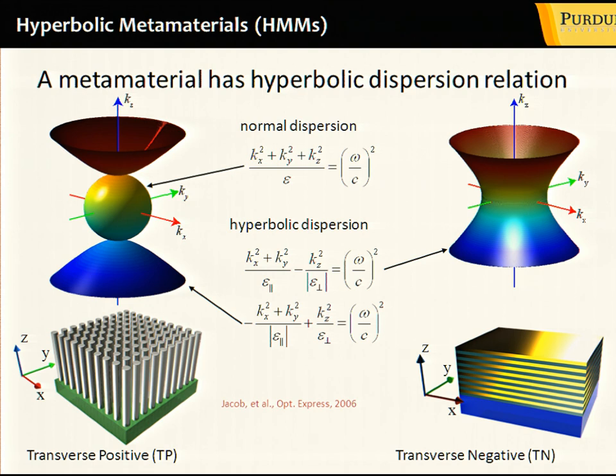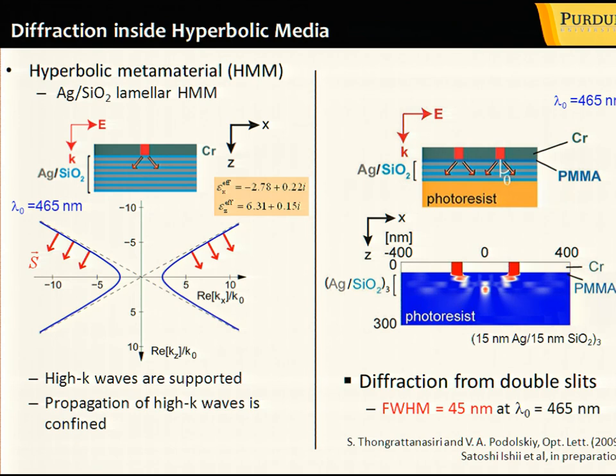However, if one of the epsilons is negative, as in hyperbolic metamaterials, which are kind of unusual, the material is dielectric in one direction but metal in another direction. So you get a hyperbola instead of a sphere, and you can have this type of hyperbolic dispersion either in a material which includes plasmonic nanowires, or in a stack of plasmonic and dielectric materials. And I will just mention one experiment which has been done by Satoshi Ishii in my group. We just used this hyperbolic material.